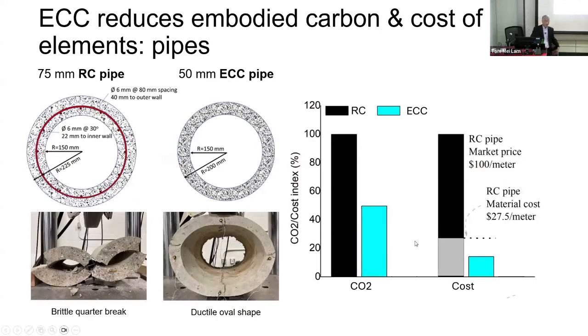Now, what if you move from the material to the structure? I only have calculations for this very simple structure. This is a reinforced concrete pipe with steel reinforcement inside. Compare that with an ECC pipe, and notice that for the ECC pipe, because of the tensile ductility, it does not require steel reinforcement. So we remove the steel reinforcement and we thin down the wall thickness.